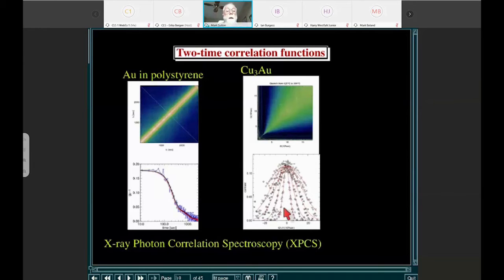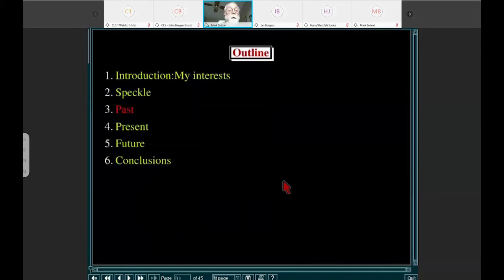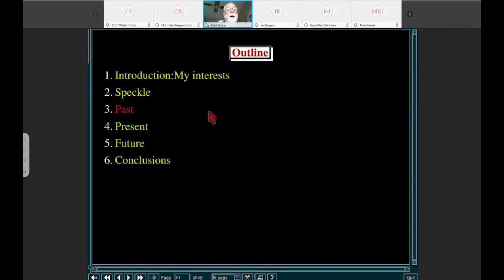As a matter of fact, for any given diagonal, anti-diagonal that we take, we get the red curve. That red curve is actually determined by one parameter, which is basically the fluctuation time, and the line shape is, for this particular sample, universal. So that's the power of speckle.